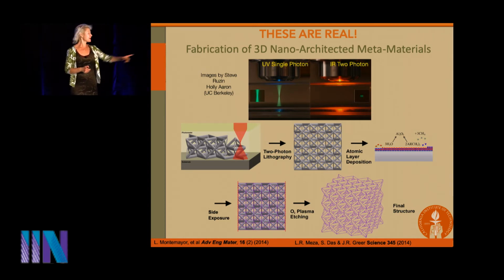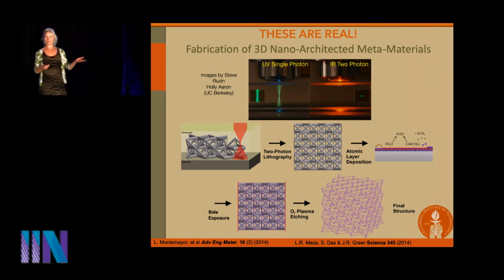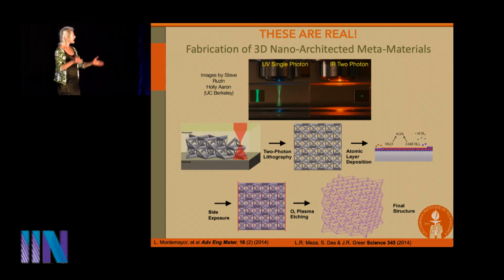This is an example of depositing alumina. It doesn't have to be alumina. We certainly have used many other techniques, but this is how we started. And then the form factors in which we typically make our samples are typically cubes, and so that allows us to expose 2 out of the 6 faces and then to etch out the scaffold that was so painstakingly written. So in the end, we end up with these hollow replicas of what we had originally designed, where the only dimension of a solid is that wall thickness of the ALD deposited alumina, for example.